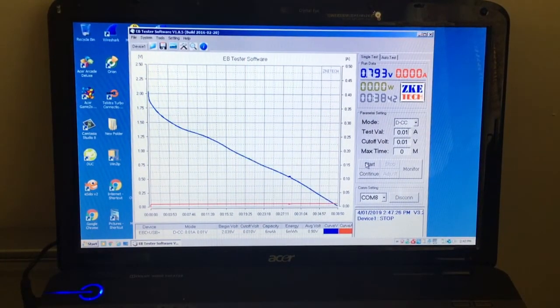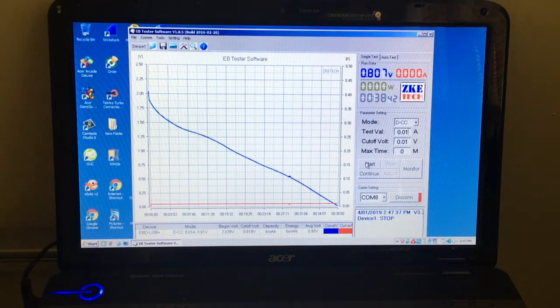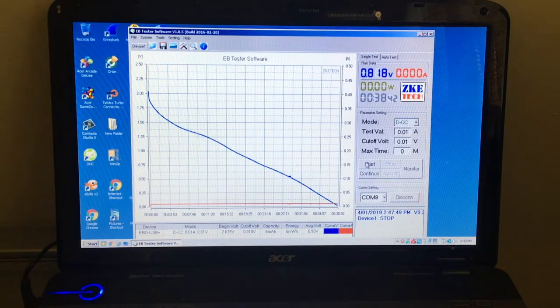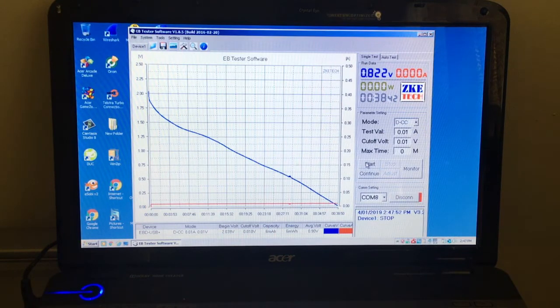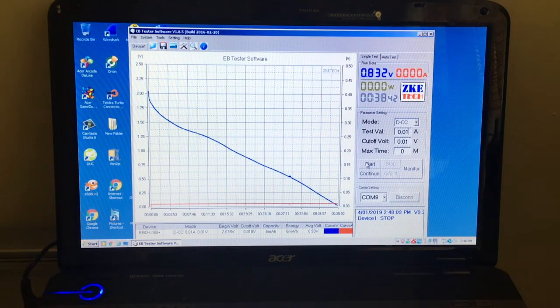For the second run, only 38 milliamps. I think the cell didn't turn out well because it was a 45 degree day when I put the cellulose acetate into the carbon mix. That should be around about the same. I think a lot of the material actually stuck to the container and not onto the cell itself. I'll probably let the cell dry out and scrape it off and show you the surface of it. It's pretty disgusting actually. I'm surprised it actually worked.